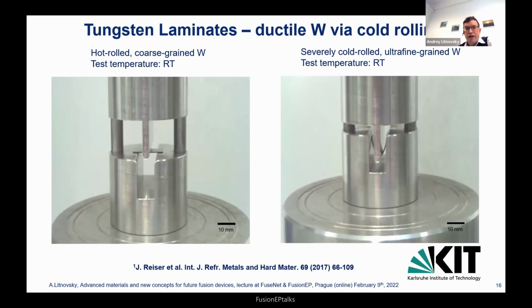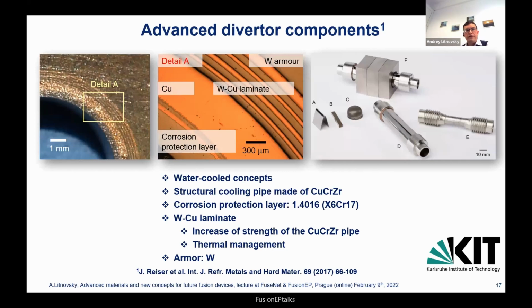And this actually gave a high impulse to a number of fusion-related applications. As you see here, this is the interior of the pipe. And this is the zoom-in on what is going on there. So you see here a corrosion protection layer, the copper interlayer. Actually, it's a copper tube, in fact. And this is a tungsten-copper laminate where you see the changing layers in between, finally ending up in the tungsten armor.